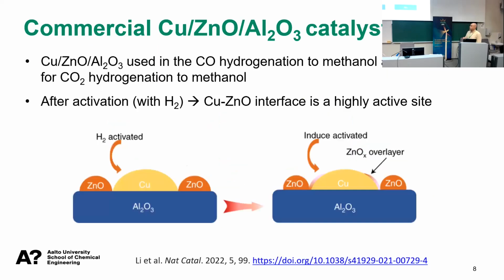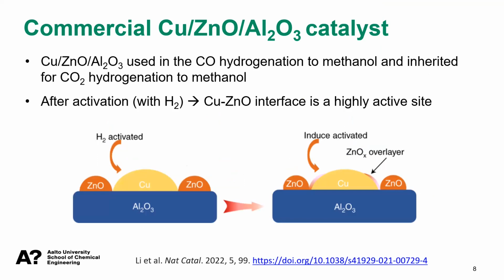it matters a lot. So then we can talk about the catalyst that we use, since this is a catalytic process. But let's start talking about the commercial copper zinc oxide alumina catalyst. This catalyst is used, or has been used, in the CO hydrogenation to methanol for decades, and it was inherited for the CO2 hydrogenation to methanol. There are many studies on CO2 to methanol with this commercial catalyst, and somehow they all agree that after activating this system with hydrogen, there is what we call a copper zinc oxide interface, which is a highly active site for this reaction. So we have to look at this interface carefully.